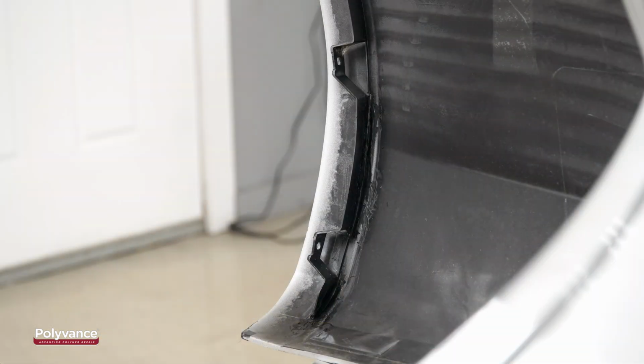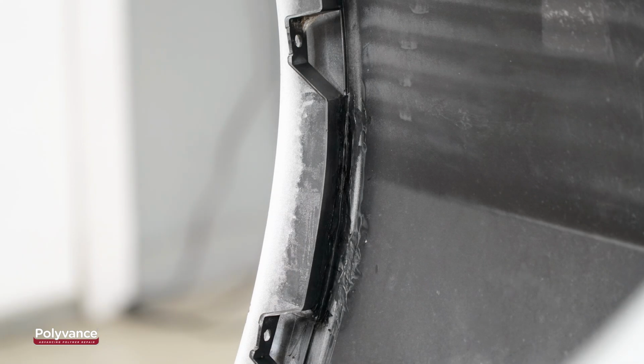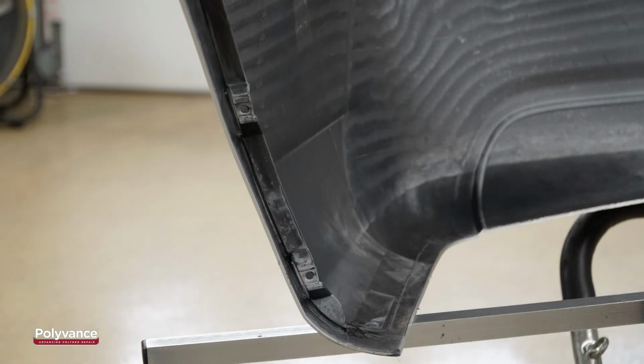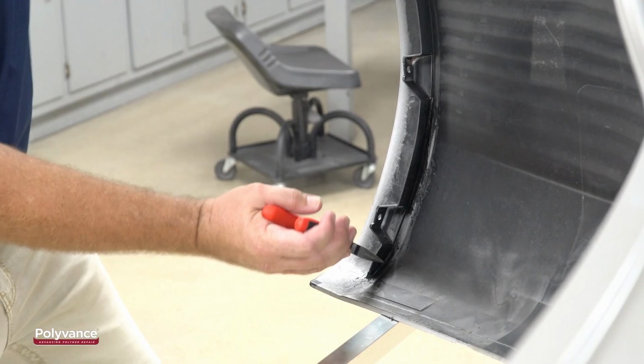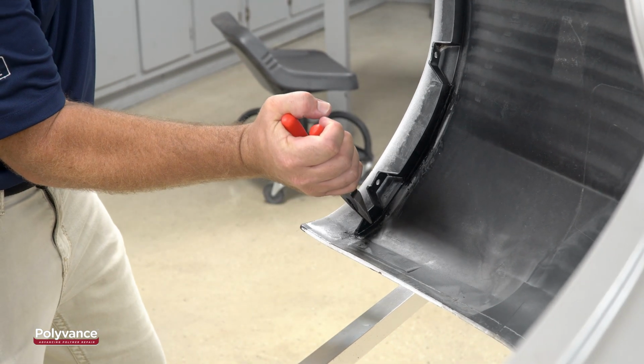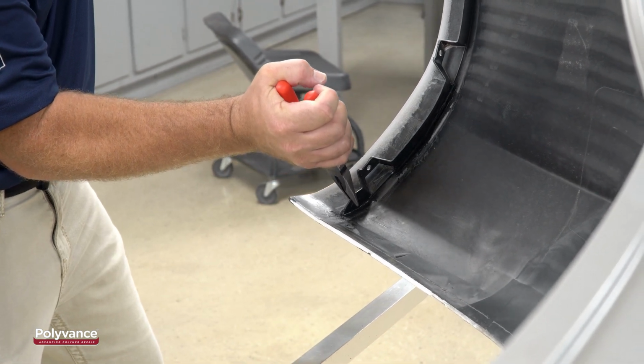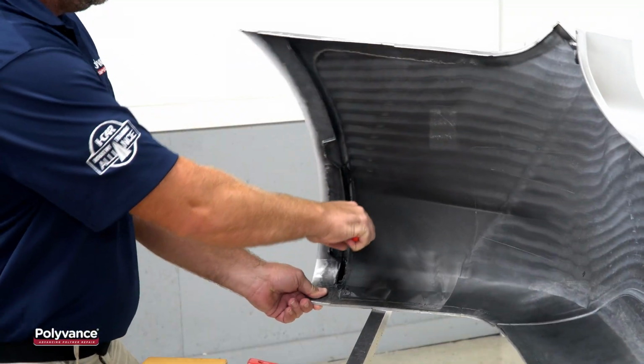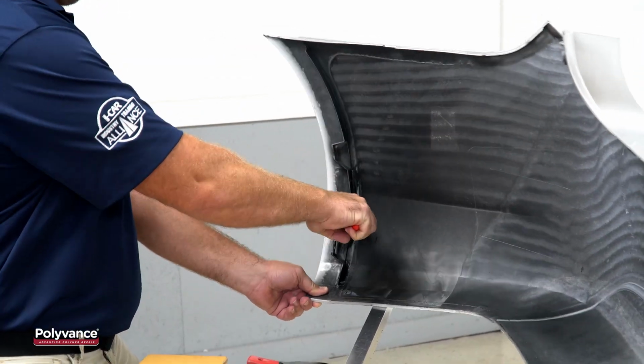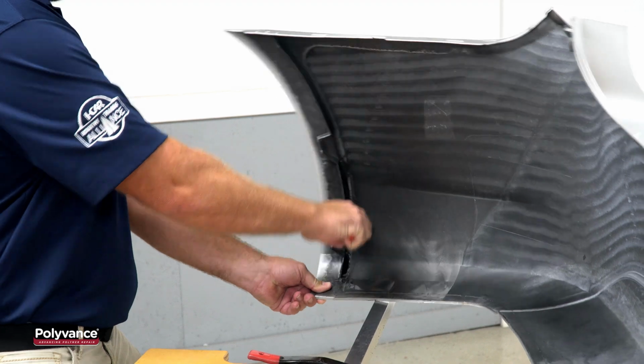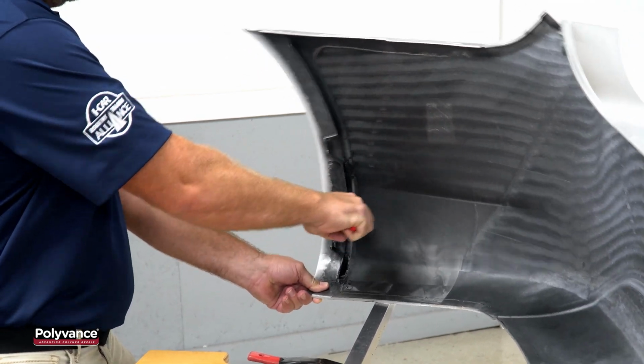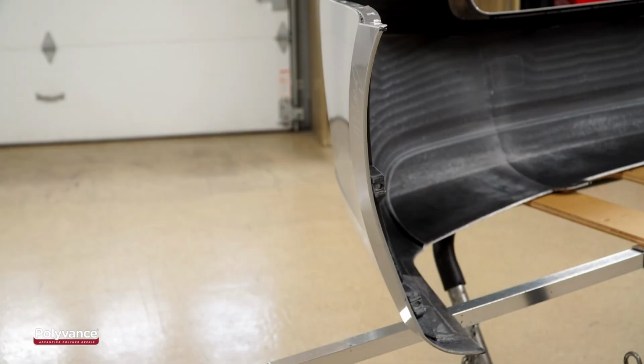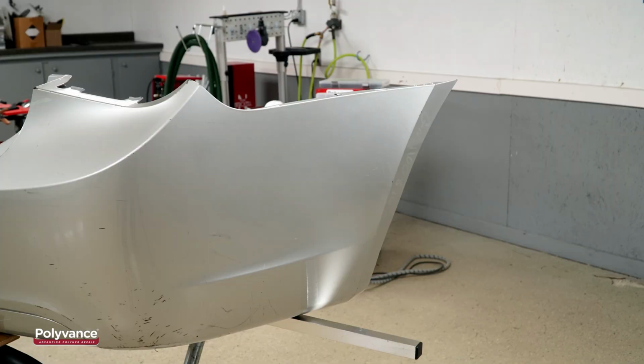Because the R02-08 corner welding rod is actually thicker than the original plastic, the repaired area should be as strong or stronger than the original. Test the strength by pulling straight out using a pair of pliers, as you see here. The flange only has to hold the inner fender liner in place, so this is plenty strong to get the job done. Also notice that there is no distortion of the plastic or the paint on the outside, so no cosmetic work needs to be done on the bumper.